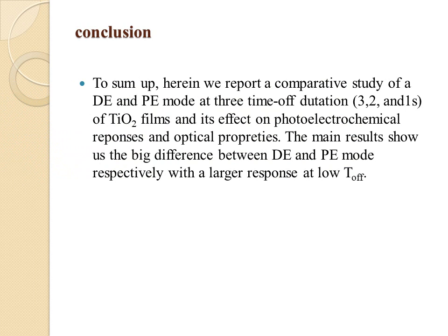To sum up, herein we report a comparative study of the direct electrodeposition and pulse electrodeposition mode at three time durations, 3, 2, and 1 second, of titanium dioxide films and its effects on photoelectrochemical responses and optical properties. The main results show a big difference between direct electrodeposition and pulse electrodeposition mode, respectively, with a larger response at low time off.